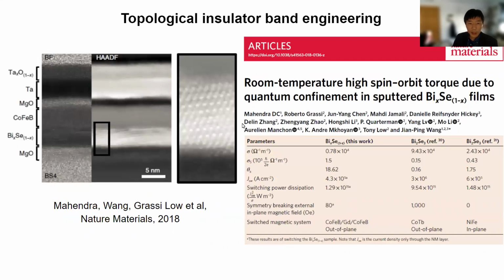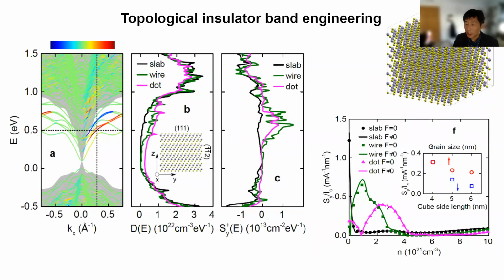This is the experiment done by Wang Jianping's group at the University of Minnesota, where they grow polycrystalline bismuth selenide. By controlling the temperature and pressure, they are also able to control the size of the grain. In the experiment, they measured the spin Hall angle, which is analogous to the figure of merit that I just showed, the ratio between the spin Hall current and the charge current. They observe a ratio of about 10, which is much larger than what one would observe in the case of a TI slab. This is consistent with the observation that having a nanostructure helps to enhance that figure of merit. They also observe this effect at very high doping carrier density, and by doing Hall measurement, they confirm that the density is around the same order of magnitude as what we observe in the calculation.